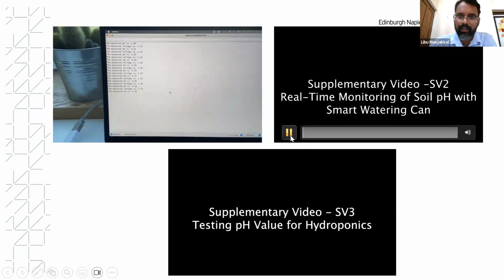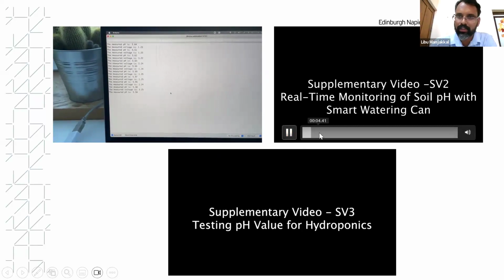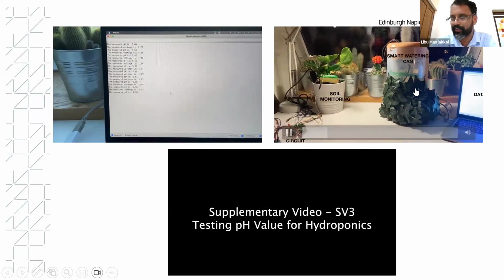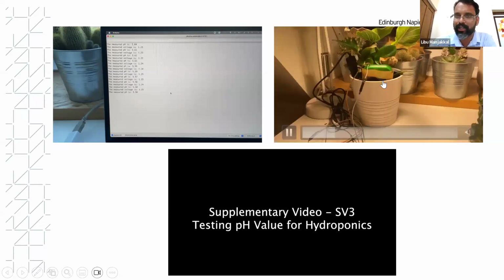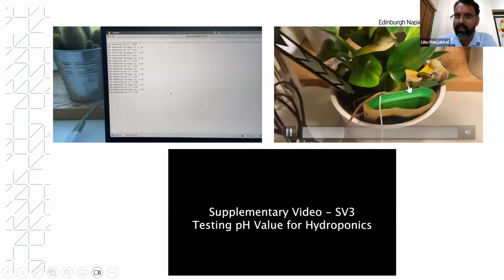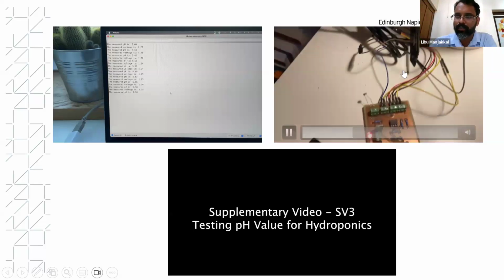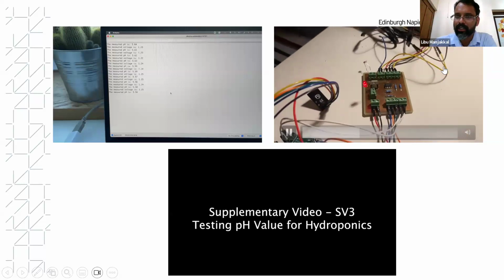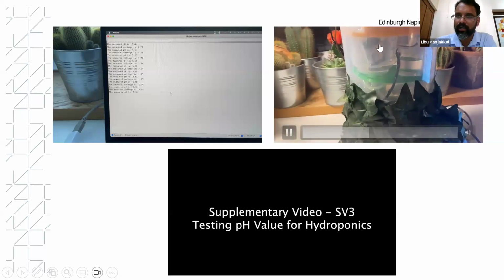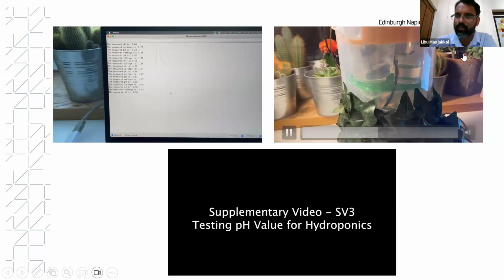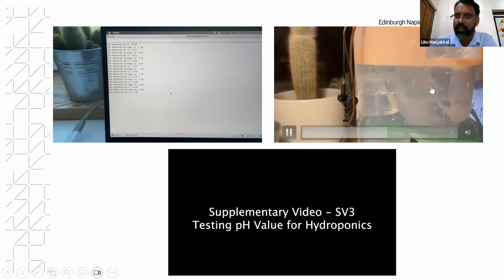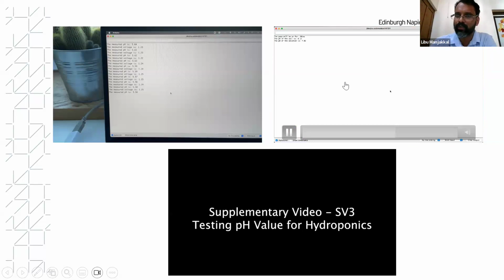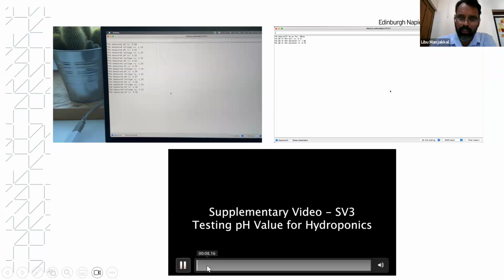And then another measurement. You can see here that this is a small setup we made in the laboratory, where we have a humidity sensor here, and we have a potentiometric pH sensor here, and then our sensor integrated on the watering can, with a different pH value of the buffer solution there. We mix the solution and drop it into the water, and simultaneously you can monitor the pH value of the solution.